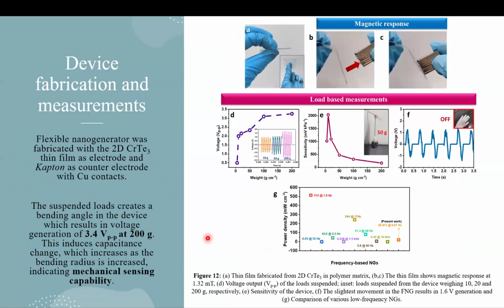So for the device, we were able to incorporate these flakes in a thin polymer matrix, which was magnetically responsive, and when applying load on these devices, we were able to see that it has the highest sensitivity with very least load, and these devices were also capable of sensing mechanical strains, and had quite a high power density for very low frequency application.